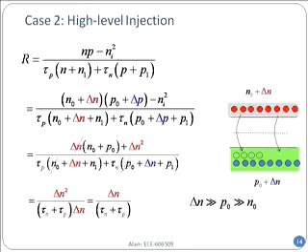Nobody is dominant. So therefore, it will depend on how quickly they can find each other. It is not that anytime an electron wants a hole, there is always a hole, or vice versa. Here, both are limiting. You have to find both at the same time in order for the recombination to occur. So therefore, you have tau sub n plus tau sub p.